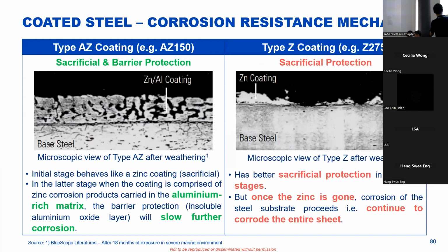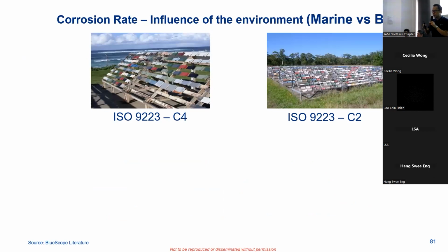From here, you can see that for the GI sample, once its outer layer is consumed, what is left is the residual steel that is exposed to the atmosphere. This is what causes the product to corrode easily. But for the type AZ, there are two alloys inside: you have aluminum and you have zinc. The zinc alloy layer is also consumed first, but what is left is the aluminum alloy layer, which helps to slow down the corrosion activity. That's why you will not see any differential rusting on the type AZ material as opposed to the type Z material. Of course, the performance of the steel will vary depending on the locations where you supply the material.